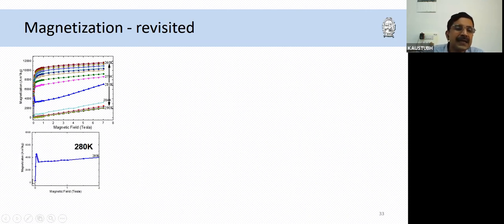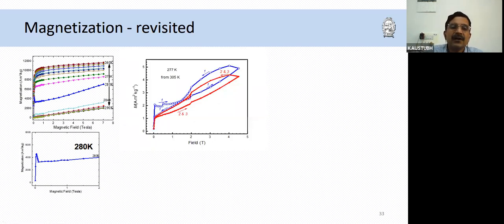and I would like to point out the magnetization curve at around 280 Kelvin. If I just isolate that curve, you can see that the magnetization initially increases and then decreases and again starts increasing. So this was just one loop, one cycle. So we completed the cycle, and this is at 277 Kelvin. We followed one type of protocol. We took the sample above its Curie temperature and cooled it in zero field from above this Curie temperature to the desired temperature, let us say in this case 277 Kelvin. Then we start measuring the magnetization as a function of magnetic field. So you can see that the magnetization first increases as shown there. Then it shows a small decrease, and it keeps going right up to, let us say, 4.5 Tesla.